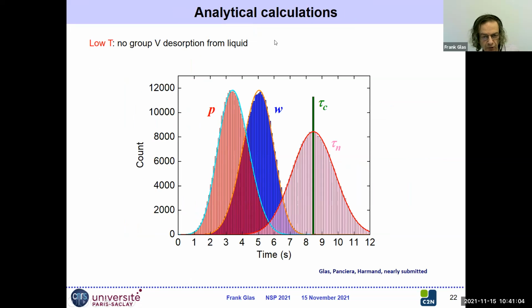Now we can do these numerical and analytical calculations. So these are calculations, and you see that the numerical calculations, which are the histograms here, are very well reproduced by our analytical calculations, which are the curves. Here it's for the propagation time, the waiting time, and the time between nucleations. But what the calculation tells us is that tau-c, which is the time between completion of monolayers, should be very narrowly distributed at low temperature when we have no desorption of group 5 from the liquid. Of course, the peak should be higher, but this should be very, very narrow.